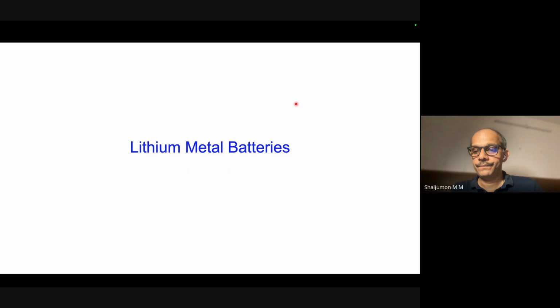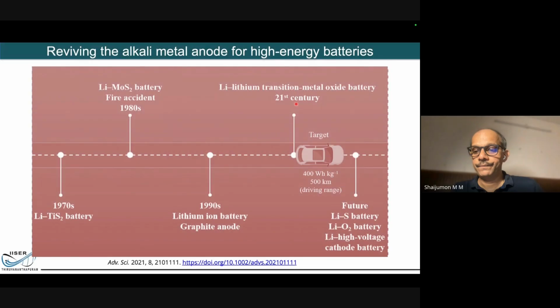Whereas in the case of lithium metal battery, the difference is that the anode remains as lithium metal. You are not going to use graphite or any other material. It is just the lithium metal that will act as the anode. What is the advantage? Lithium metal has the highest energy density, so the battery made from lithium is going to have high energy density. But then the catch is, why are people not looking at it? Because safety is a problem. Because I'm using lithium as such, dendrite formation and all kinds of safety issues are going to pop up.